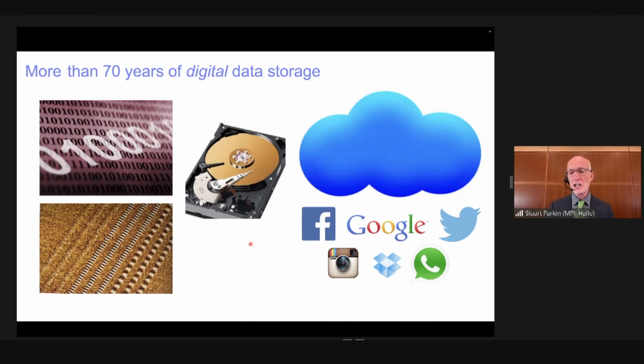Nevertheless, the concept is you have a glass disc which is rotated at high speed. On the surface of this disc is a thin magnetic film, and the magnetic film is magnetized in tiny regions. The magnetic moment direction today is either perpendicular up or perpendicular down to that magnetic film. And then on top of the surface of this magnetic film is a reading and writing device, which is moved laterally over the surface of the rotating disk to both write and to read the digitally encoded information.